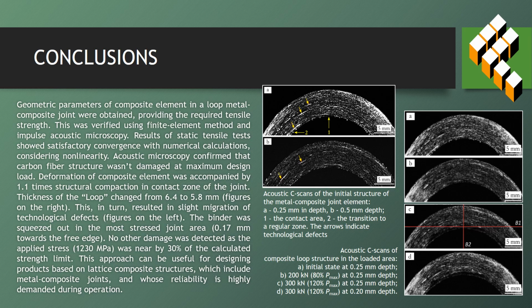Deformation of composite element was accompanied by 1.1 times structural compaction in contact zone of the joint. Thickness of the loop changed from 6.4 to 5.8 millimeters. Figures on the right. This in turn resulted in slight migration of technological defects. The binder was squeezed out in the most stressed joint area. No other damage was detected as the applied stress was nearby 30% of the calculated strength limit.